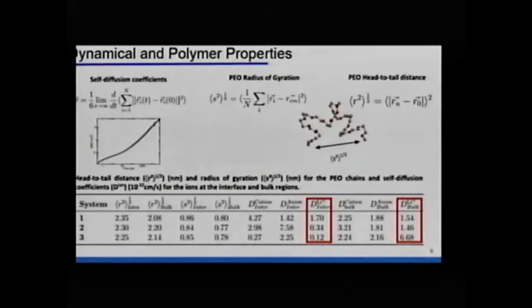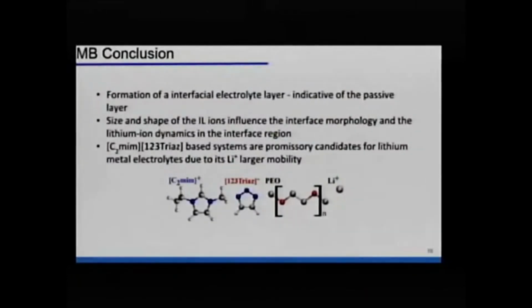ions in the system. So as a conclusion, we have the formation of the interfacial electrolyte layer, which is an indicative of the passive layer with these ionic liquids that we show here. The size and shape of the ionic liquid ions influence the interface morphology and also the lithium ion dynamics. And if we had to choose right now one system to take to the lab and do some tests, I think the imidazolium triazolide is a good candidate for lithium metal battery electrolytes.